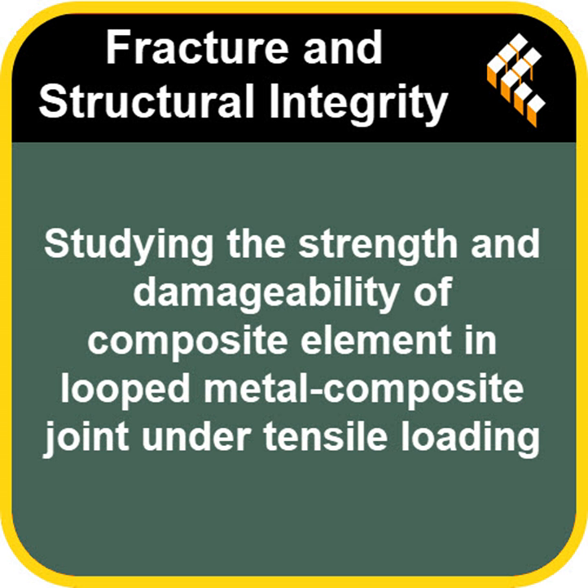This is a really profound insight, I think. The material isn't just passively taking the stress. It seems to be reorganizing itself at this micro level. Reorganizing. Yes. The study concluded that the increased external load and the compression it causes in that contact zone contributes to the compaction of the composite structure. Gets squeezed tighter. And they could measure that.